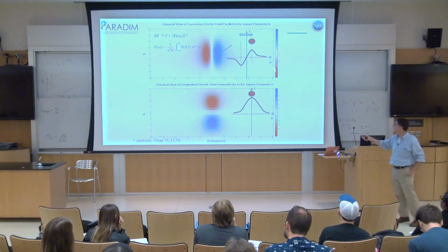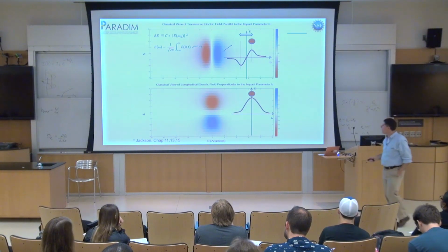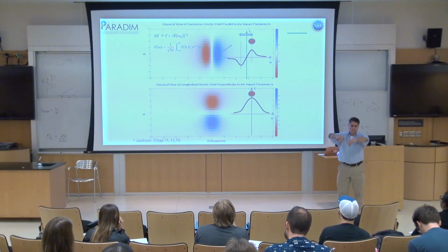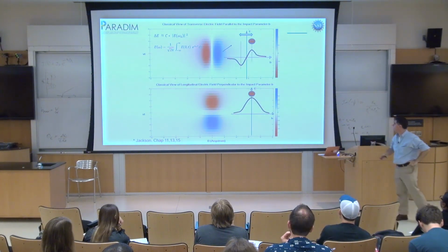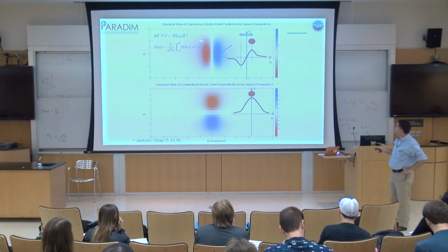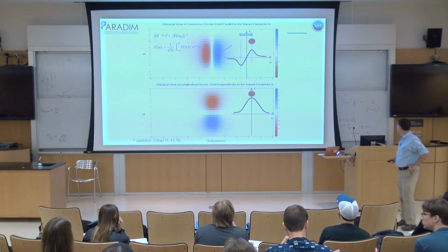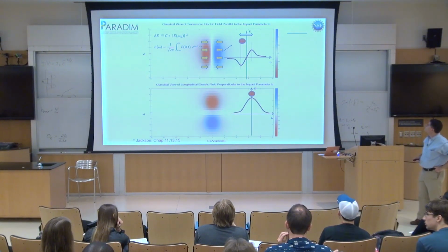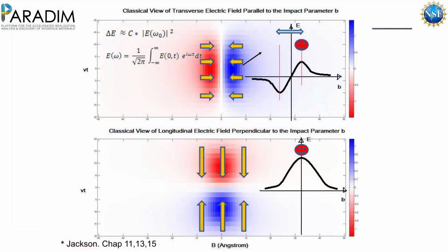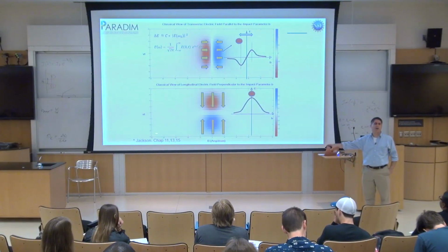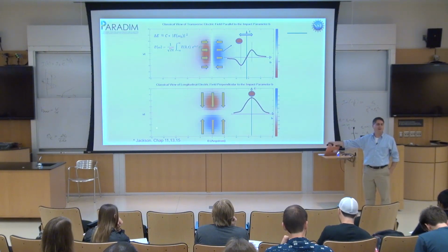This is a nice thing to excite a dipole. And then if I'm doing the longitudinal field, I have the electron here. Before the atom, I'm pushing it away, and after the atom, I'm pushing it back the other way on the other side. So I get two little field pulses that look like this. When I do the Fourier transform of my electric field, there's my atom coming across, I'm going to get a nice analytic function. This becomes a K0 Bessel function. That becomes a K1 Bessel function. This is all classical, and it's in the three nicest chapters in Jackson. These are my three favorite chapters.